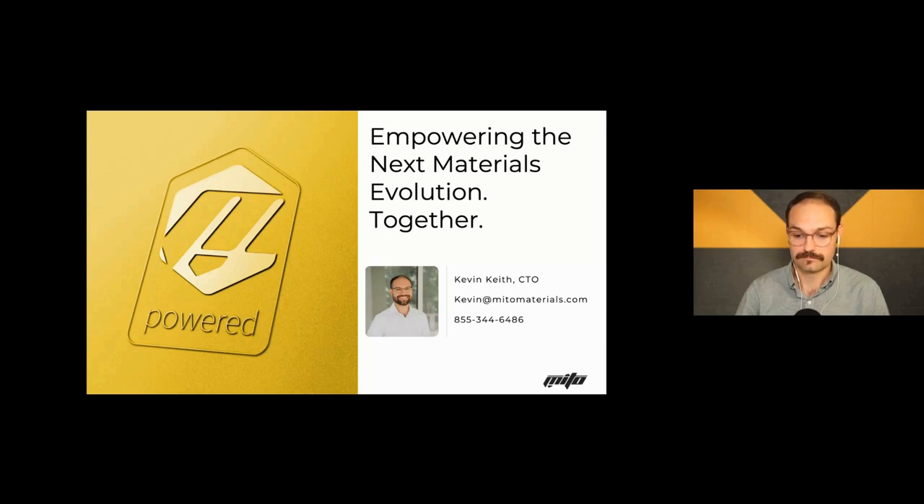What can you say about graphene as an additive for injection molded products? It plugs in — as long as you can compound it into the pellets, you're good to go. I haven't seen a problem with going into injection molding. I've seen it go into pultrusion, extrusion, and injection molding. Film blowing is questionable because it's also dictated by morphology and crystallinity — if you have too much of a nucleating agent, when you blow out the film it'll just break apart.